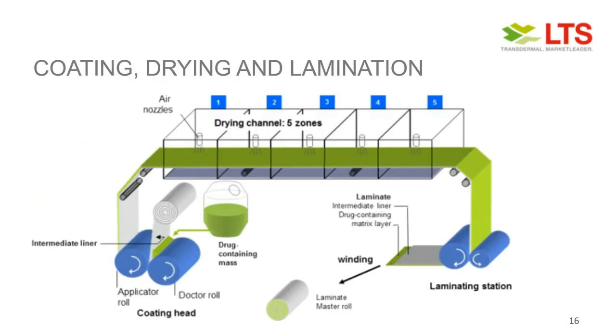So here we have exemplary a mid-size coater at LTS, having 5 drying zones. On the top you see that. And we bring the drug-containing adhesive mass around the coating head. We transfer the mass into the coating head. Here it's a 2-roll coater. And we coat onto a process or intermediate liner through the coating head, and the mass is transferred into the drying channels. It's dried, for example, from top, just with an air stream. It's like an air fan.